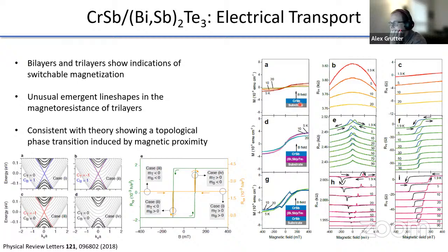So of course, the chromium antimonide doesn't really show anything interesting on its own. You have a non-hysteretic longitudinal magnetoresistance and a linear anomalous Hall measurement. You have basically no magnetization signal. If you grow bismuth antimony telluride underneath chromium antimonide, you get a larger magnetization, you get hysteretic magnetoresistance and a hysteretic anomalous Hall effect. And then if you sandwich the bismuth antimony telluride in between the chromium antimonide, what you find is a very strange anisotropic switching behavior in your longitudinal magnetoresistance, and you see a large anomalous Hall effect, even larger than in the bilayer case.